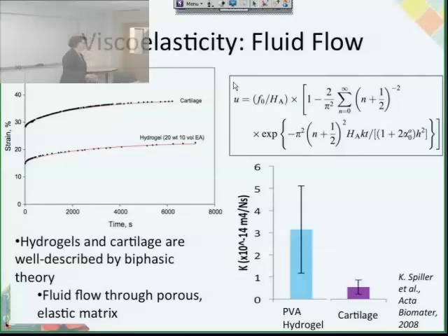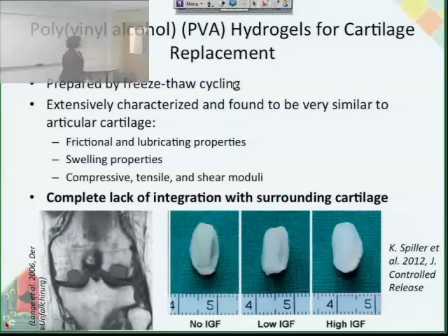So that was the reason why this hydrogel would never behave the same as cartilage, because it didn't have that fixed charge density. And that's why cartilage is so stiff, because it can resist the mechanical forces, because that fluid can't flow as much as it would if it were just a hydrogel. Because the fluid is incompressible, and because it can't flow, you have major resistance to applied forces. So that's a really interesting material that we have not been able to replicate in the lab. Not just my lab, anyone.